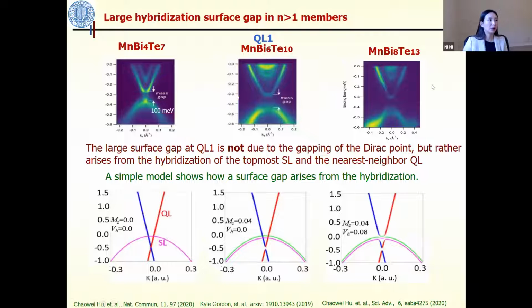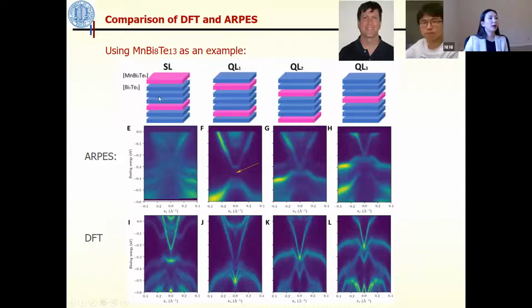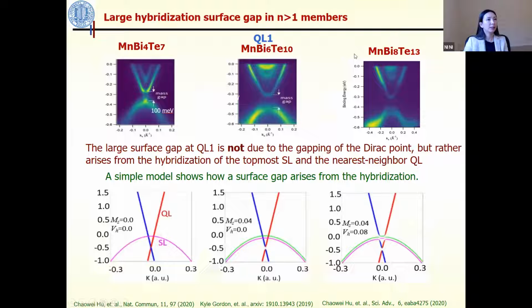Something I want to draw your attention to: if you look at all of them, for the QL1 layer, which is the layer just on top of the 124 layer, in 147, 1610, and 1813, you can see they show the largest mass gap, around 100 meV or even higher. The larger the gap, the more stable it is. It means the QAH will be able to be realized at a high temperature, and it will be pretty stable.